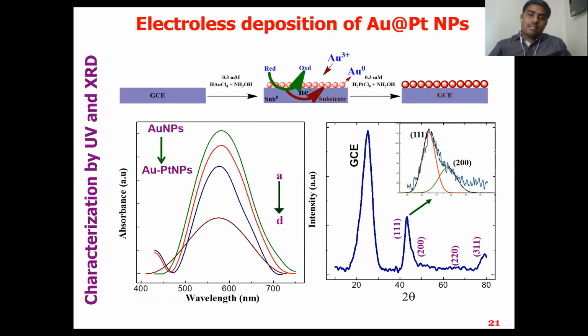The other case is direct electroless deposition of gold platinum nanoparticles. In the previous gold platinum nanoparticles, we synthesized them in solution. Here we didn't. We directly fabricate the gold platinum nanoparticles from the metal precursor without synthesizing the material.